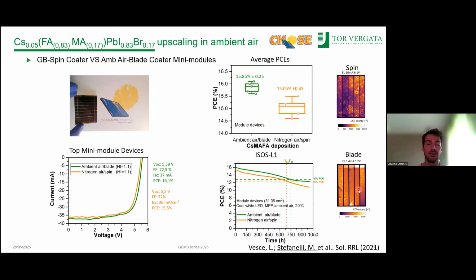You can see, even if the PCE is not state of the art, the gain in efficiency is more relevant for the ambient air blade-coated perovskite. Also, the analysis that we did on these modules clearly highlights that spin coating is not a technique for large areas, because the centrifugal force together with the comet effect can of course produce more defects